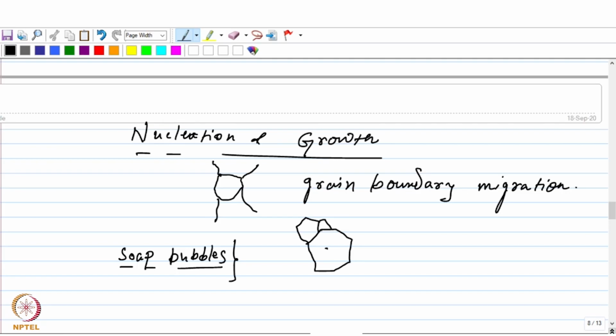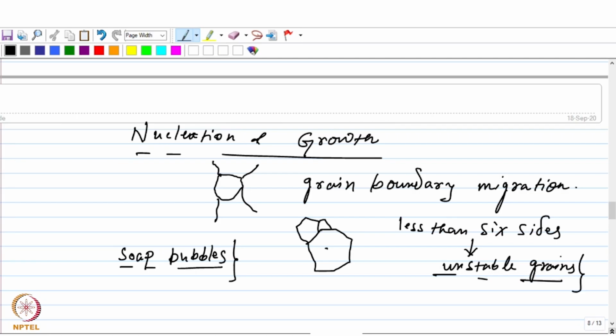Okay, now if you look at the growth of these bubbles as a function of time, you would find that grains having different numbers of sides will form, and the ones which have less than 6 sides will be actually unstable. So these are the grains which will tend to dissolve. In this case, these will be the bubbles which will disappear, and the ones which have 6 or more sides will grow at the expense of these unstable grains, right?